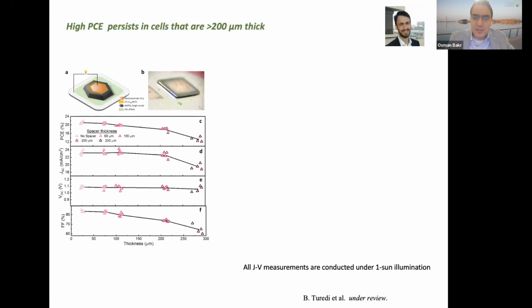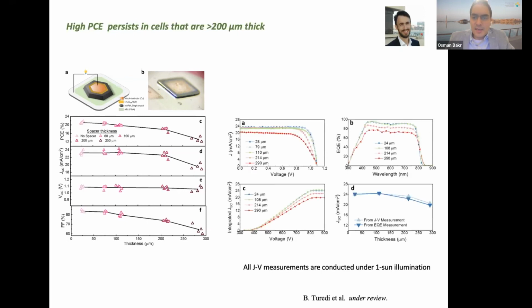It's only at the really extreme range, at 300 micron range, where the current collection starts dropping and the efficiency starts dropping. But here you have solar cells that are a few hundred microns, almost 400 times thicker than what people normally make, and they still collect current efficiently. And so that surprised us.